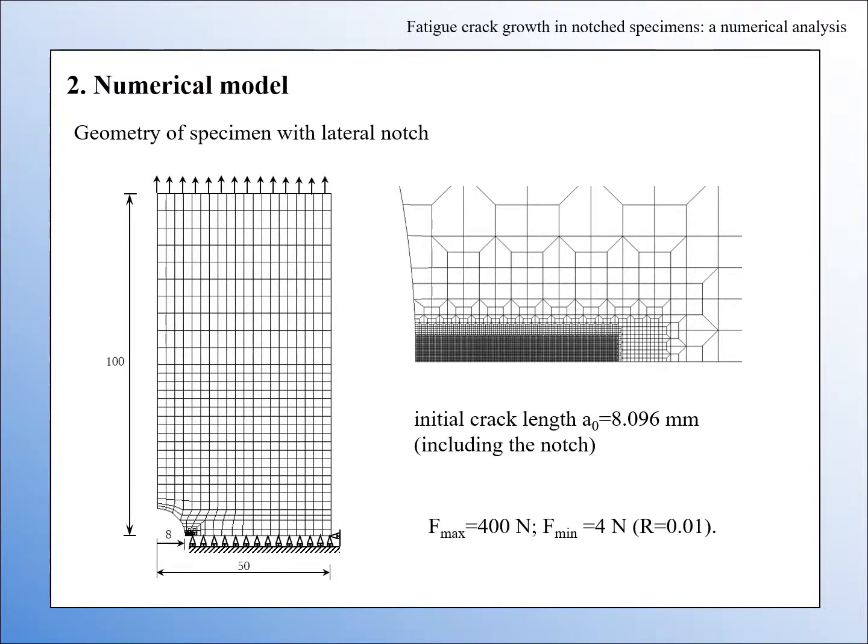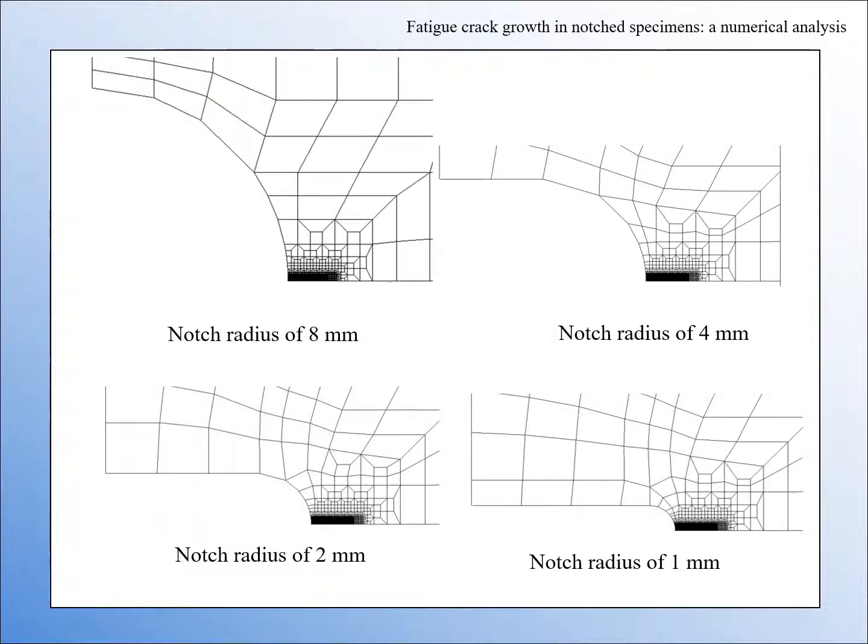The notch has a length of 8 mm. From this notch a crack was modeled numerically and the specimen was submitted to tension loading. Four different notch radius were considered for the notch, as can be seen here.